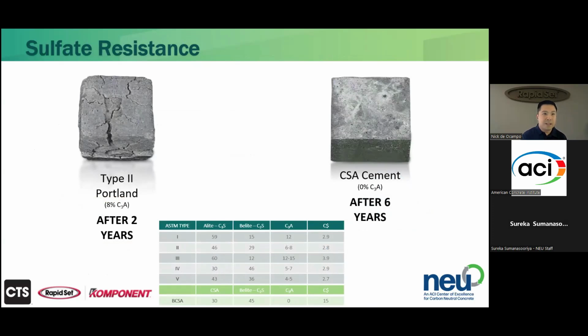One last thing related to chemistry before I get off chemistry - sulfate attack in Portland cement. I talked about this way back, looks like 45 minutes ago now, that because delayed ettringite formation is the mechanism for sulfate attack in Portland cement, even with a type 2, which has a little bit less C3A and higher sulfate resistance, after 2 years in a sulfate environment, that cube on the left sees some significant deterioration as delayed ettringite formation occurs.